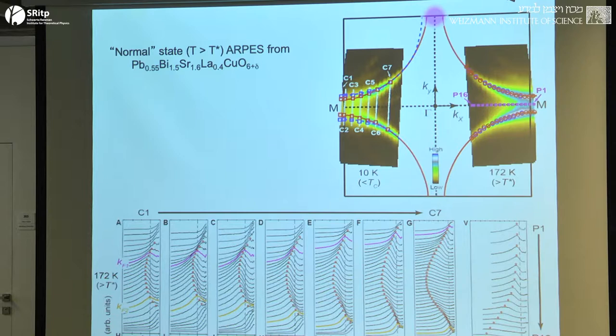But in single-layer BISCO, it turns out that the pseudo-gap temperature is rather low, and so it's possible to get into the regime above T star, in this case at 172 Kelvin, the pseudo-gap temperature is about 150 Kelvin, and to measure the electron spectral functions. And the electron spectral functions look quite simple. Here's the electron spectral functions. Here we're seeing intensity as a function of binding energy for different cuts through the Fermi surface. And so you see some peak. It disperses up to the Fermi energy. It's got some fairly simple shape. It's got a peak and a width. And so, that looks a little familiar. But now let's zoom in on this here.